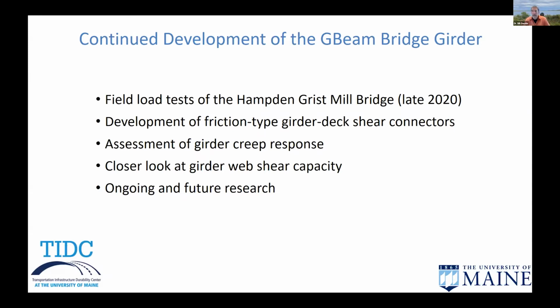As the first of its type, it was really important to go out and load that bridge and assess how it behaved. We also want to talk about what we're doing now in terms of Girder-Deck shear connectors. There have been major advances made there. We've also taken a look experimentally at creep response of the girder. That's a bit of an unknown going into this. It's not something where we can just say, well, camber the girder for 1 times the dead load deflection, which is pretty typical for a concrete girder, which also undergoes creep. Because again, this is a hybrid with FRP and concrete behaving compositely together.